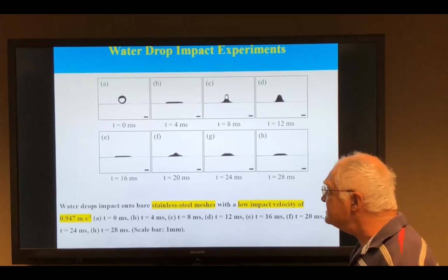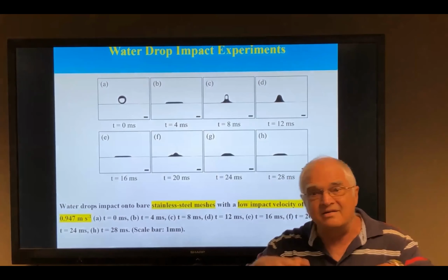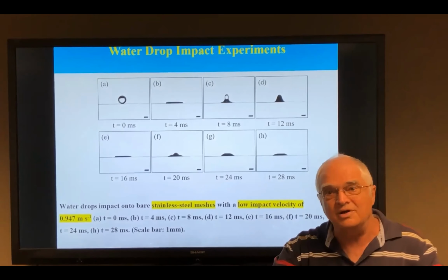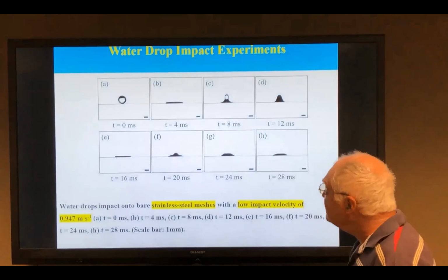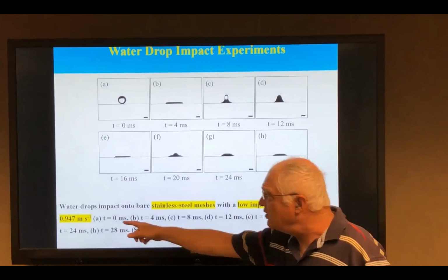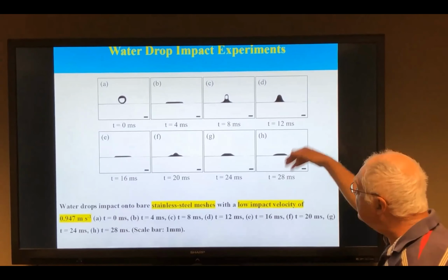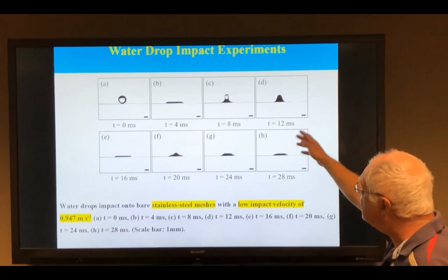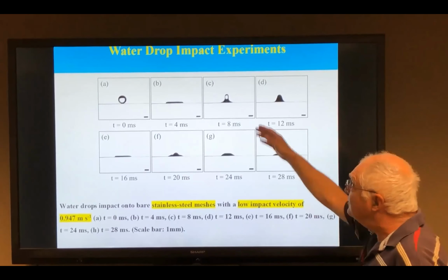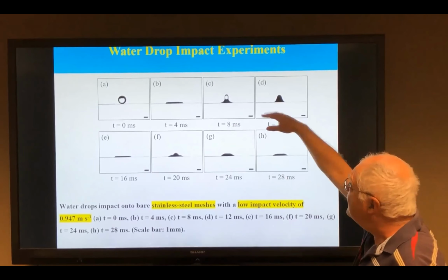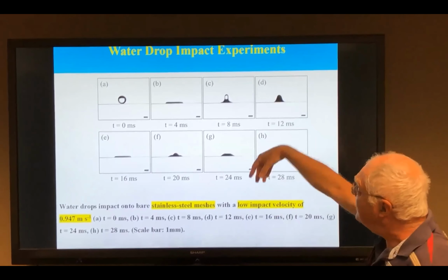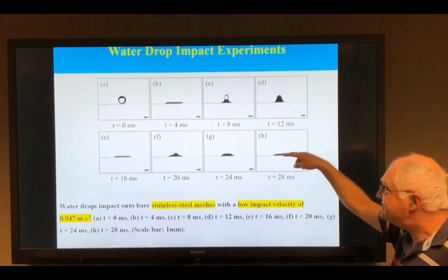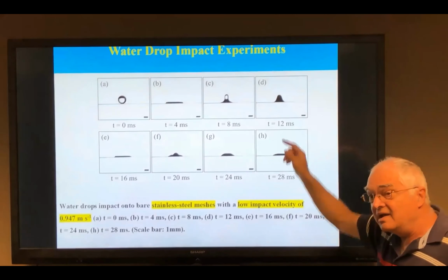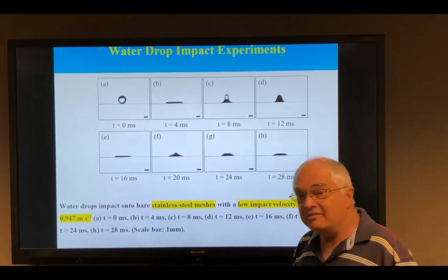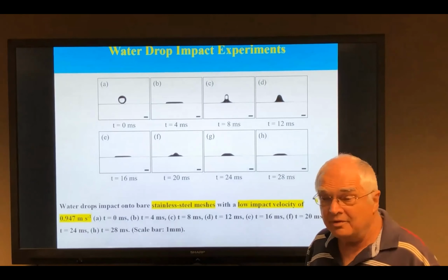So the first experiment is not with a membrane, but with a metal grid which will be used as a support for a very thin membrane. You drip a droplet with a relatively low velocity of about 1 meter per second onto the grid, and you see this time development on the scale of milliseconds, and everything is good. The droplet hits the grid, oscillates back and forth, and ends up on the outer side of the grid. This is a good sign for the grid, which does not even pretend to be super hydrophobic. Okay, it just protects.